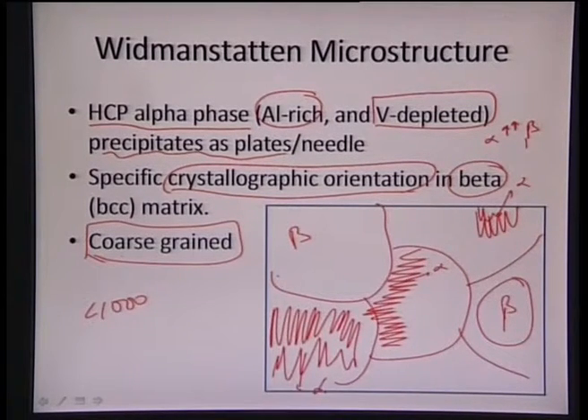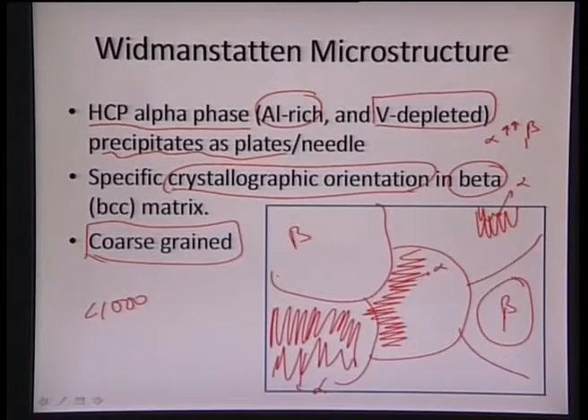We are taking it to very high temperature, we are letting it be there for much time, and then we are doing a very slow cooling. That is the reason the material undergoes higher thermal exposure for a very long time, and that is the reason the grains remain very coarse. And again, we see that the alpha is getting precipitated in the BCC-type beta matrix along certain crystallographic orientations, and that is the reason it appears more like a needle-like structure. This needle-like structure can create very high stress concentration effects along the needle edges, and that is the reason it is a very poor structure.